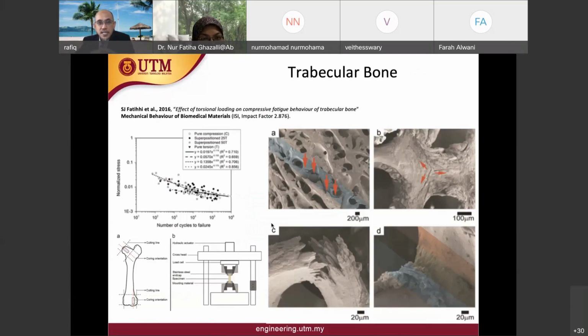In the previous two slides, I showed you the results from compression testing. Now this one is torsional loading, on compressive fatigue behavior of trabecular bone. We modified our Instron equipment so that it can do torsion repeatedly. It's a cyclic behavior, and you see the fracture sites of the cancellous bone under this torsional loading.